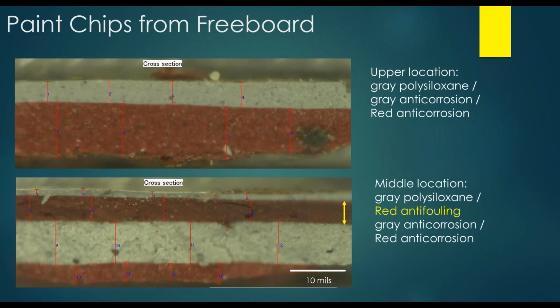When we looked at the paint chips from the freeboard using an optical microscope, we found a difference between the areas where the paint was peeling, in what we've referred to as the middle location, versus the area where the coating was intact in the upper location. What we found was the presence of an additional and unexpected red anti-fouling layer in between the gray polysiloxane and the gray anti-corrosion coating. This suggested to us that the coating failure was the result of an inadvertent application of the red anti-fouling coating above the boot top.